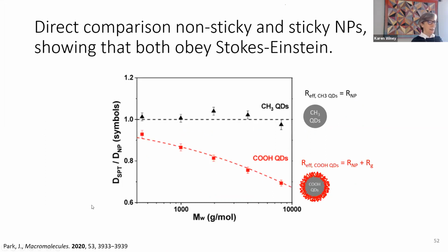So this is the single particle tracking normalized by straight up Stokes-Einstein. And in this case, the particles are the same as the core particle size, the non-sticky ones. And then the sticky ones, we have an adsorbed polymer layer, which is the same size as Rg.